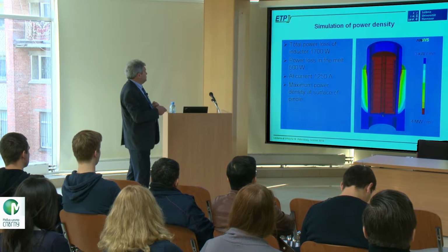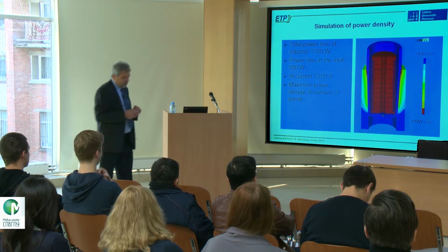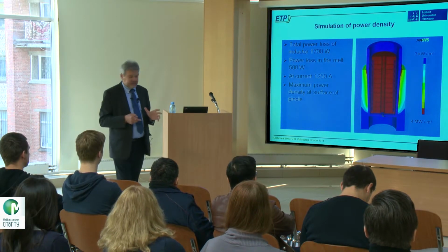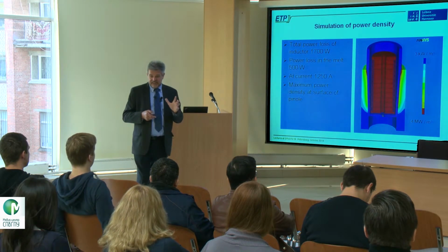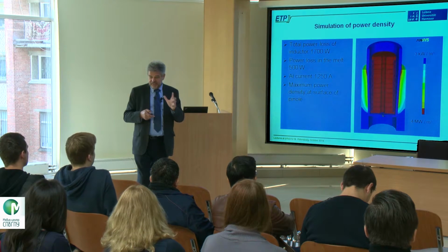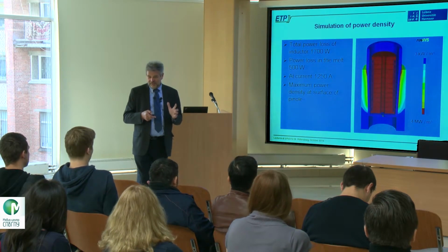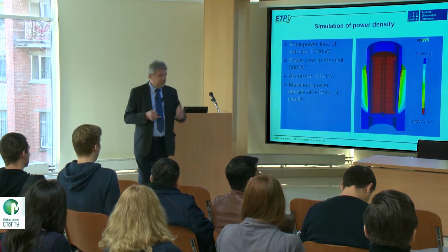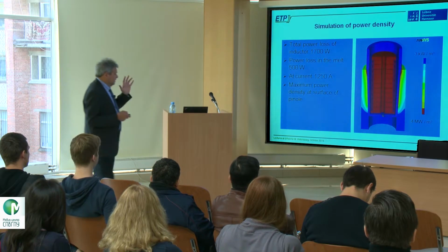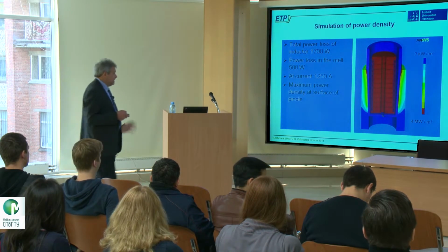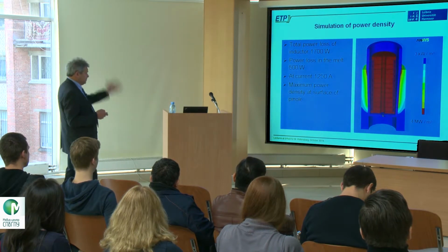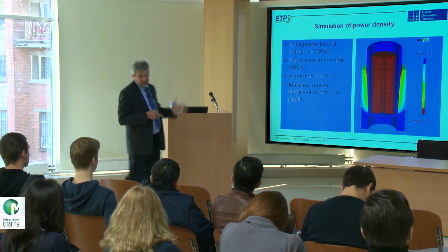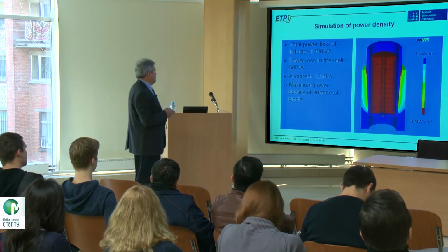And here you have the power density. Power density also was important, because if the power density is too high, what does power density mean? That means heat. If the heat is too high, you cannot solidify. You always keep the temperature. So the Lorentz forces should be low. No, it should be high, sorry. The Lorentz forces should be high, but the power density, the Joule heat, should be low. This was a clear aim.